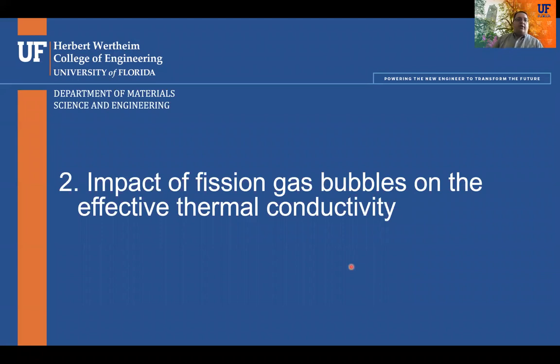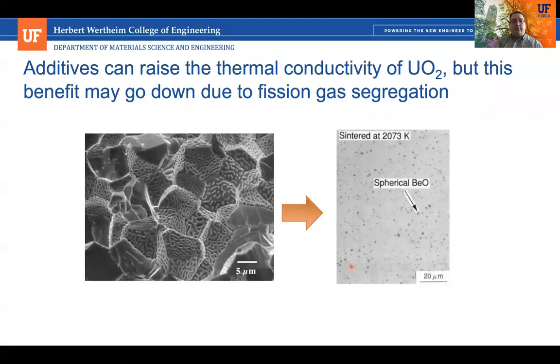So we've shown then that these high thermal conductivity additives definitely have a benefit. They can raise the thermal conductivity without significantly lowering the amount of fuel, and we can get a benefit in lowering the centerline temperature. However, once we put them in a reactor, things start to change. Experiments have actually shown, even in shorter irradiations, that certain materials like silicon carbide are not even stable. You heat it up and irradiate it, and the silicon carbide just disappears. But other materials like beryllium oxide have been shown to be stable even at elevated temperature and radiation.